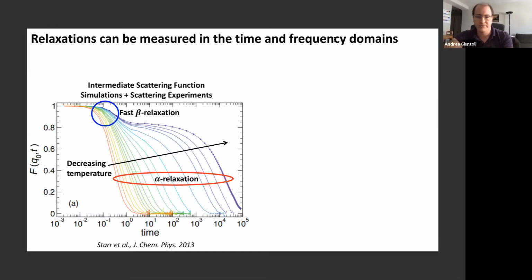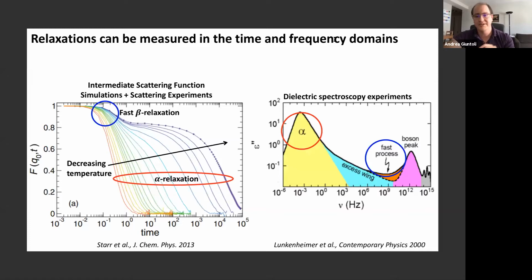So that's one way to measure it. And typically simulations or scattering experiments do it this way. Another way, in the frequency domain, is via dielectric spectroscopy, which means that you excite your system with an oscillating electric field, and you see at which frequencies the system resonates. So you'll see a broad peak for the alpha relaxation, whose frequency will change depending on the system. And then always near the picosecond, you'll find this fast process. And you'll see also this boson peak, but ignore that for now.